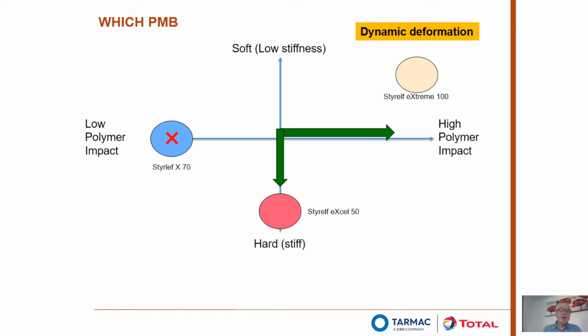If you look at something like a mid-range polymer, in this case the Styrelf eXcel 50, we're looking a little bit stiffer because it's a harder bitumen, but of course we've only got a mid-range polymer impact. So it could do some good. It depends upon the particular design you're looking at, but it's going to contribute from being stiffer and it's going to contribute from having an interim polymer impact. And then, of course, if you look at the Styrelf Extreme 100, it's not stiff at all. It's very low stiffness, but it has such a high impact from the polymer that it can resist because of the amount of recovery that it's going to give. Let's look at that in a bit more detail.